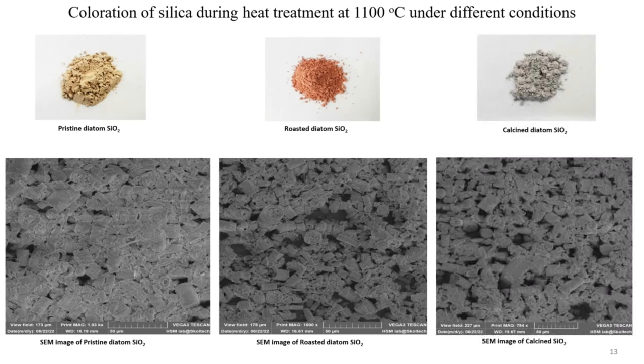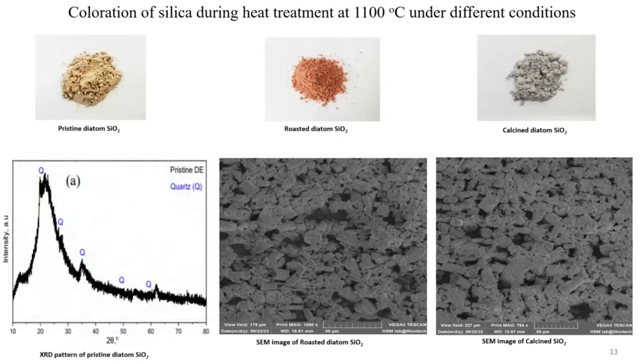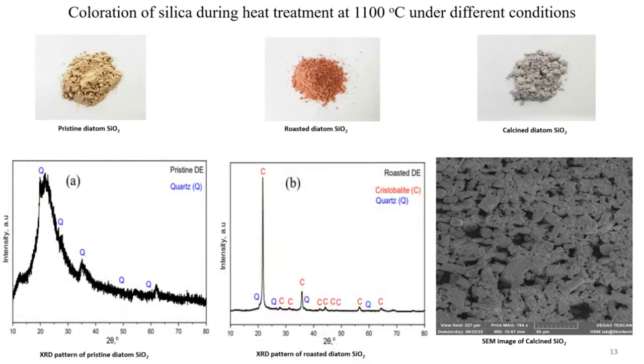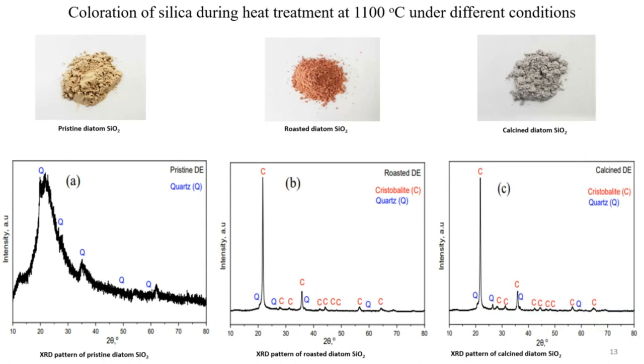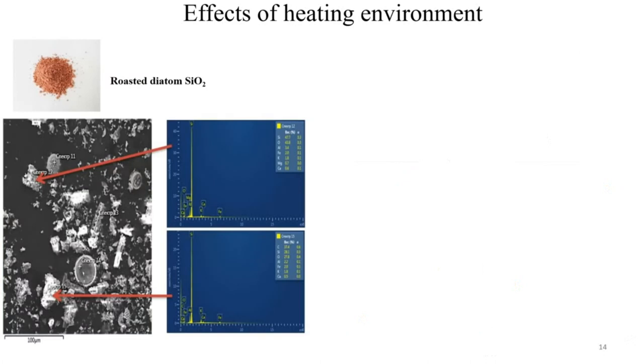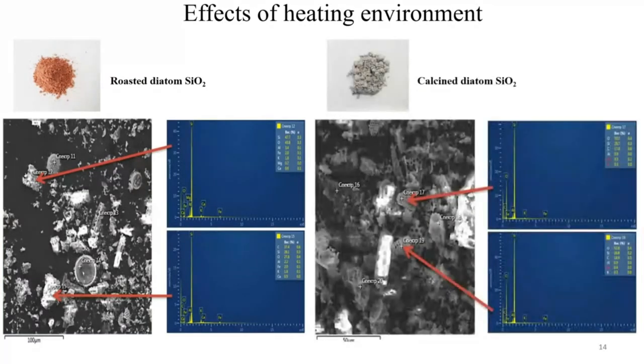The difference is just a matter of the environment, but both treatments yielded quite different color changes, but the drastic color change was with the roasted diatom silica. Another interesting thing about the heat treatment procedure is that it is able to unclog all the pore areas in the pristine powder, because during heat treatment, a lot of impurities are decomposed. And XRD analysis also confirmed crystallization of these powders with the main phase as alpha cristobalite in both roasted and calcined silica. So the effect of heat treatment was further explored, and it was interesting for us to understand the effect of the environment on the coloration.